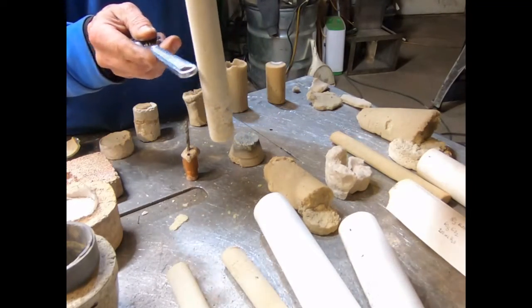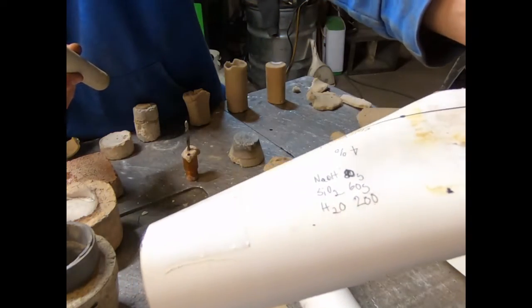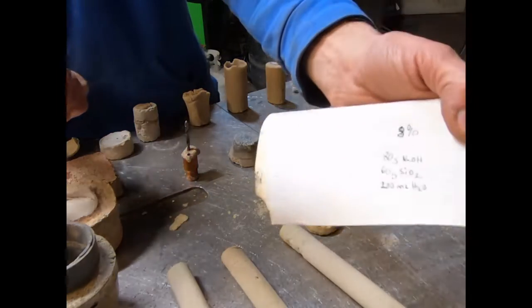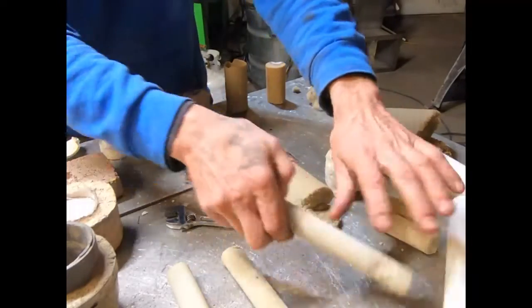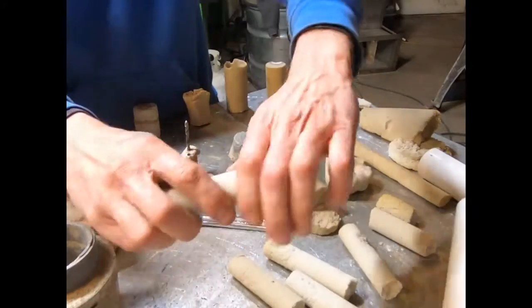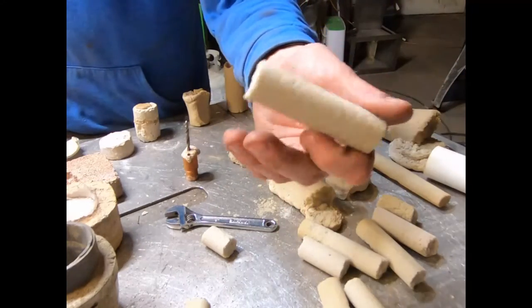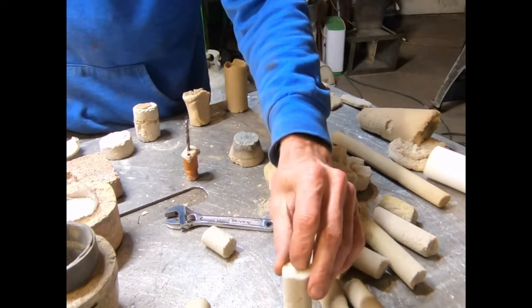They don't sound the same at all. This is composition B — and this one here I believe I got hot, and this is 8%. So they break pretty easy — not a whole lot of structural integrity there. That one seemed to be the stiffest. If you make this composition and then get it hot again it will melt on you unless it's been cured with CO2 or heat treated.